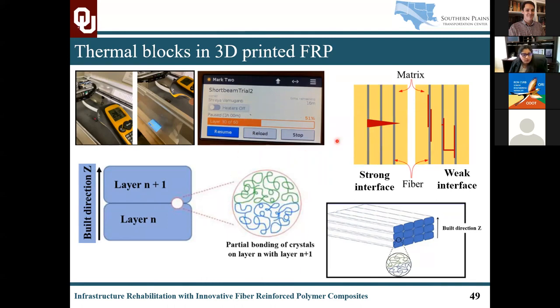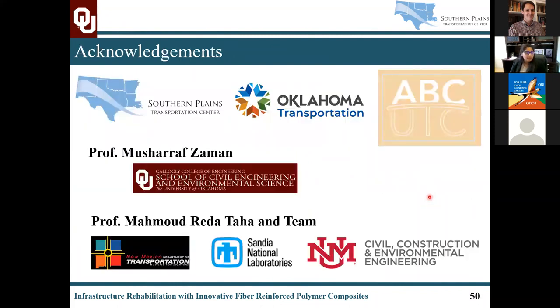After we affect those interfaces, strong and weak interfaces can behave very differently from each other. Matrix and fiber interface can be strong, but the crack propagates very easily between layers. But if the interface is weak between the matrix and the fiber, we have much more interlaminar and along the fiber direction failure that can result in very different mechanical behaviors.